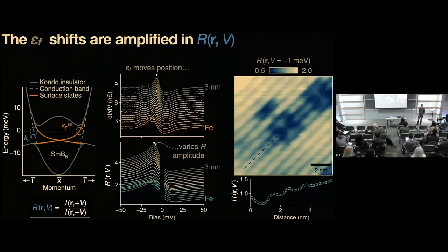Right, but I don't have to use theory. I'm just saying from the experiment, you would extract two different length scales. Well, many experiments extract many different length scales. If you look at the thermal conductivity, the length scale you get for the mean free path is about 10 nanometers. That's consistent with this picture. If you look at the Dingle factor from quantum oscillations, the length scale is like 50 nanometers for the mean free path. So it's difficult to say, I think. Okay, thank you.